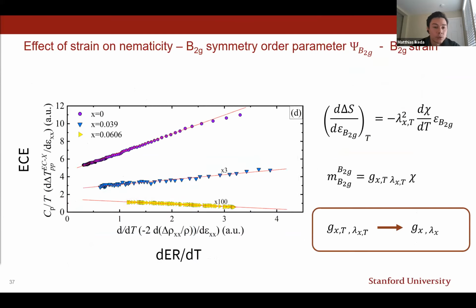And this is what I would like to show you on the next slide. So the elastocaloric effect is proportional to dER/dT. For the elastoresistivity, we know that the elastoresistivity should be proportional to the nematic susceptibility, but there are proportionality constants, namely G, which is a coupling constant of nematic degrees of freedom and charge carriers, and also the nematoelastic coupling lambda. And if we now were to compare these two quantities, we find that the elastocaloric effect should be proportional to the temperature derivative of the elastoresistivity only if G and lambda were not temperature dependent or not strongly temperature dependent.